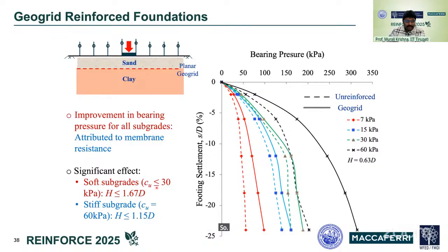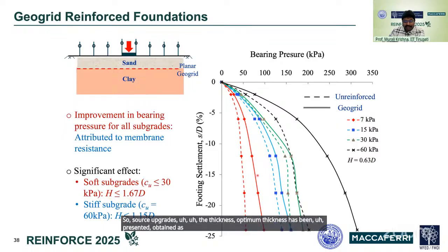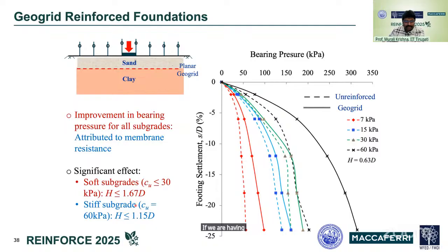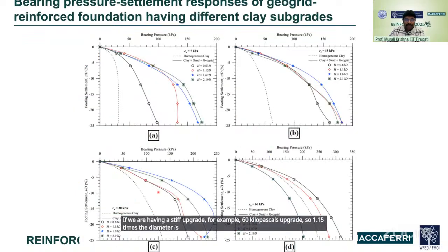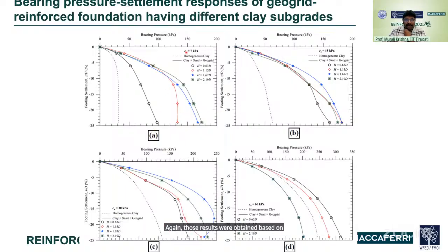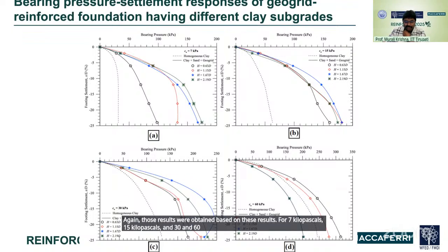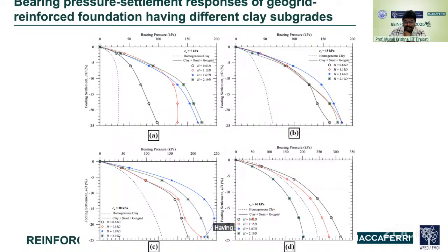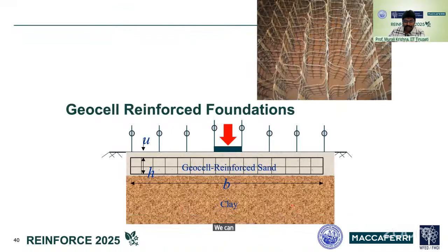For soft subgrades, the optimum thickness has been obtained as 1.67 times the diameter. If we have a stiffer subgrade, for example, 60 kilopascals, then 1.15 times the diameter is the thickness we can obtain. Again, those results were obtained for 7 kilopascals, 15 kilopascals, 30 and 60 kilopascals, having the homogeneous clay and clay sand bed with geogrid, and how the different performance could be obtained. These pictures are self-explanatory.